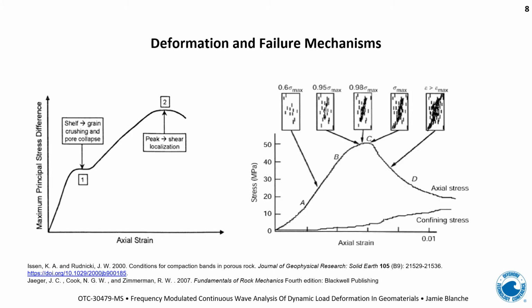So in experimental geomechanics, it's common practice to present your data as a stress-strain plot, which is ultimately telling you about the load versus time and deformation of your sample. So the left-hand graph here is explaining some of the stages in which deformation will go through within cemented sandstone. As the principal stress or the vertical load on the sample increases, you get some axial shortening or strain of that sample, where it typically barrels out a little bit at the middle, but generally it's getting shorter. And then you start getting grain crushing and pore collapse. This is represented by the shelf at point 1 on the left-hand graph.